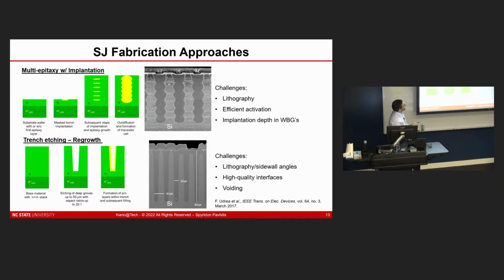But all of this requires very well-controlled litho, because you have to do this multiple times, efficient activation of implanted species, and in order not to do this too many times, hopefully the ability to implant at a very deep level as well. You can also do trench etching and regrowth. So you etch out a region and put in a layer within that. That not only requires good litho, but also requires high-quality interfaces.